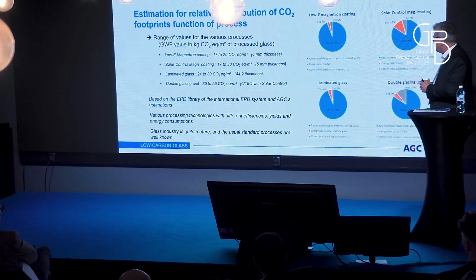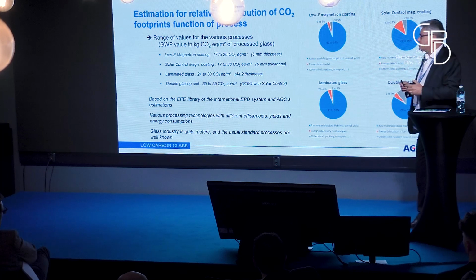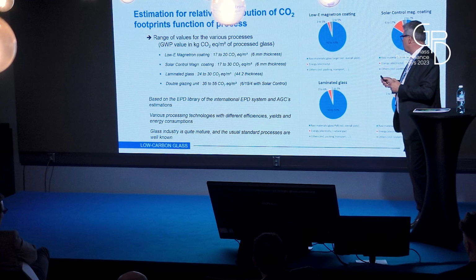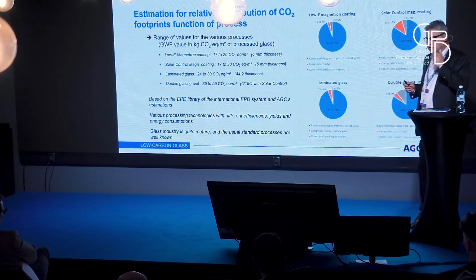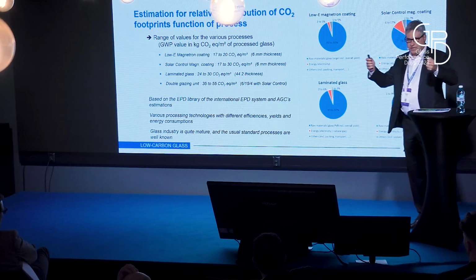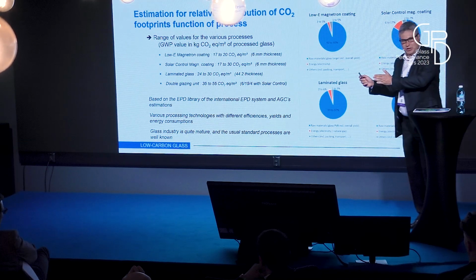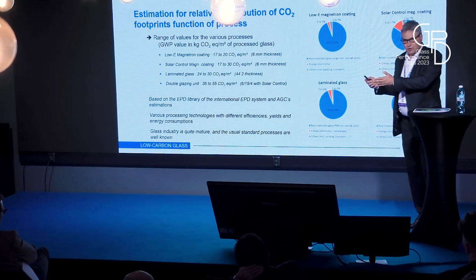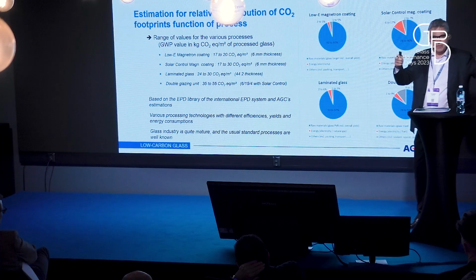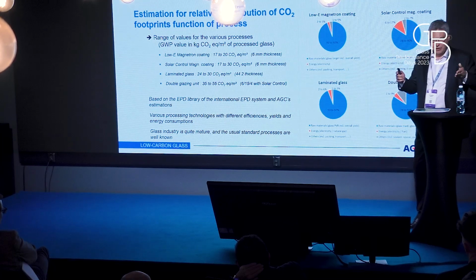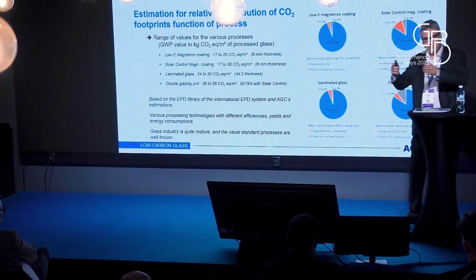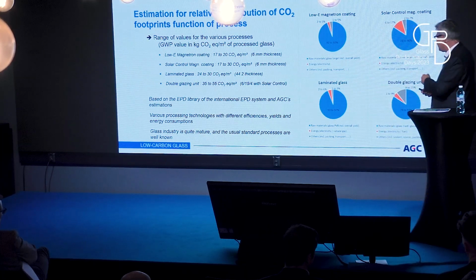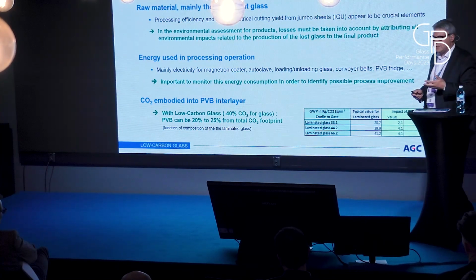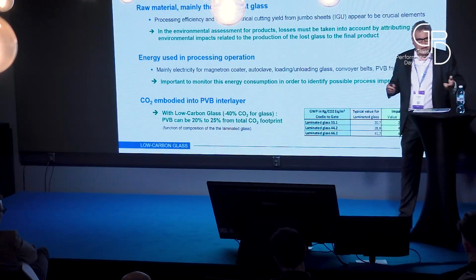Anyway, you can see the pie with the CO2 origin, CO2 footprint, and you can see that the raw material is the blue part. It's the most important for all the transform. The raw material includes the cutting loss, because of course we take the jumbo, but we cut to make windows, and a part will be lost, but this part has some CO2 embedded and has to be reported in the square meter per square meter of final product. We have to do it honestly, not just count what is on the windows, but all the process from the beginning. The second is the energy, and the third is all the other. In case of double glazing, it's the sealant, the frame, and things like this.